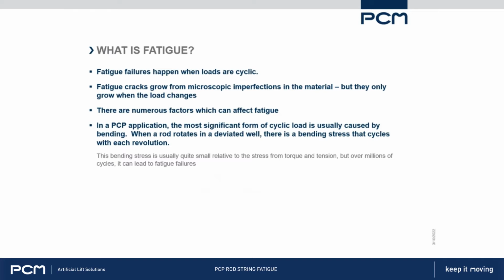There's also cycles that are due to slugging, for example. If you get slugs of gas or slugs of solid going through, you get spikes in the torque. If those are happening frequently, then that's also going to be making the fatigue problems a bit worse. Those are generally only a problem if you've already got a fatigue problem from being in a deviated well, or if your torque is very, very high, or your overall stress in the rod is very high. If you're operating very close to the yield stress, then those slugging events can take that stress above the yield, and that will lead to early fatigue failures as well.